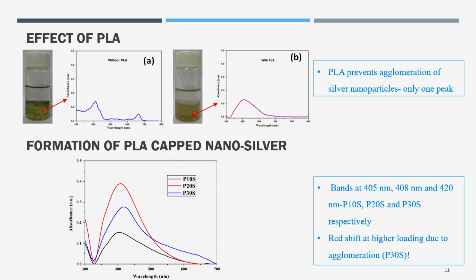If you look into the right-hand side, it is with PLA. There is only one hill. What does it indicate? Only one absorption happens in the system, which means the system is not heterogeneous, it is homogeneous, because only one signal, one pulse, is generated. When more and more pulses are generated, that shows heterogeneity within the system. Only a single signal is the first confirmation that the absorption is uniform. So that's the first evidence we got that PLA helps, which reinforced our concept.